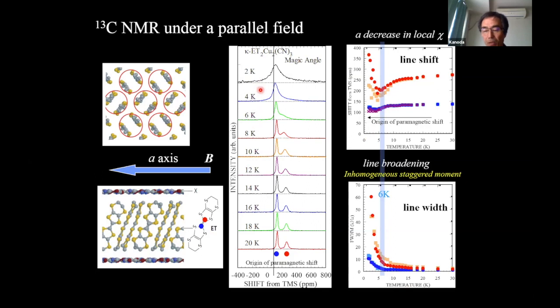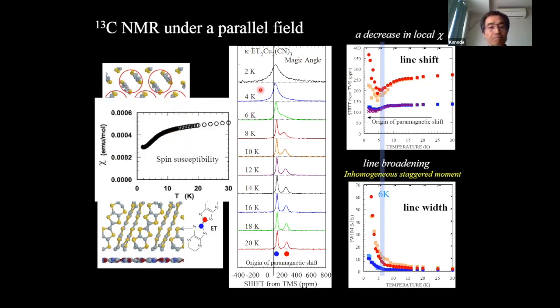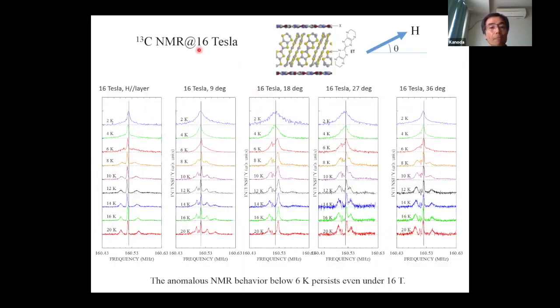So the anomaly is at 6 Kelvin. We increased the applied magnetic field up to 16 Tesla. You see, the NMR spectra are complicated depending on the field angle. The angle against the plane direction is changed. But the behavior is essentially the same. Several line positions appear depending on the different hyperfine coupling constants. But the situation is the same for all lines. This line has a positive hyperfine coupling constant, but this line has a negative hyperfine coupling constant. However, at low temperatures, all of the lines converge to the Knight shift zero position.